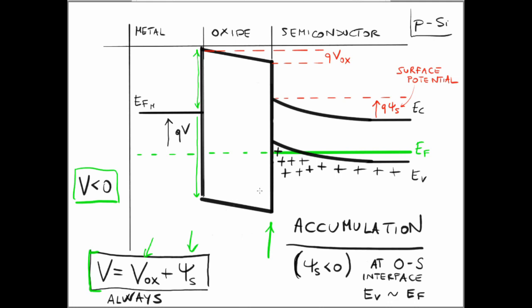Now it's hard to say at this very moment what they are. It's only by solving the Poisson equation through the entire device that we could say what their values really are. Nevertheless, with this type of bending that we see, what we should expect is that because the Fermi level very close to the interface is now approaching the valence band a lot, the majority carriers, we are in P silicon, remember, so the holes are majority carriers, will very happily accumulate even more toward the interface, so the interface is becoming even more P. And so we call this situation, where the majority carriers are accumulated at the interface, accumulation.